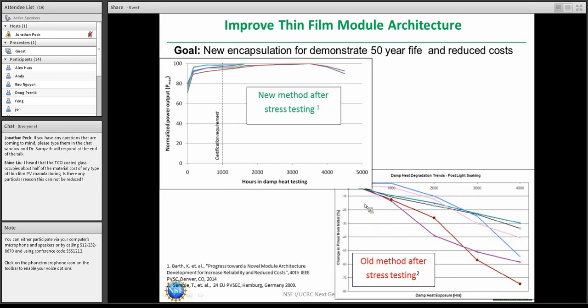degradation. But the current method that is used in the industry today, you can see that they don't last that long. They don't employ all of these advances that have come from this process. They do pass the 1,000-hour requirement. So if you were only looking at 1,000 hours, which is the requirement from the IEC test, they all pass that 1,000-hour test. But there is now thinking in the field that to go to a 50-year life, we may want to extend this requirement not to 1,000 hours, but go on up to 4,000 hours, and that is the old method, and this is the new method that we are currently working on.